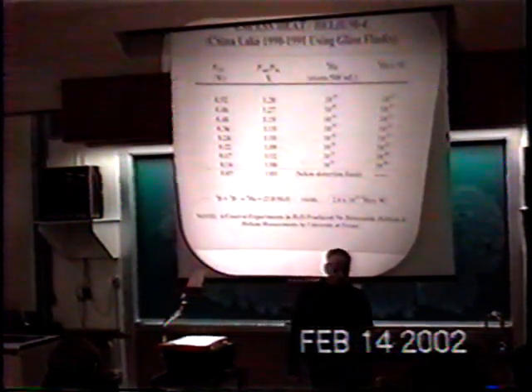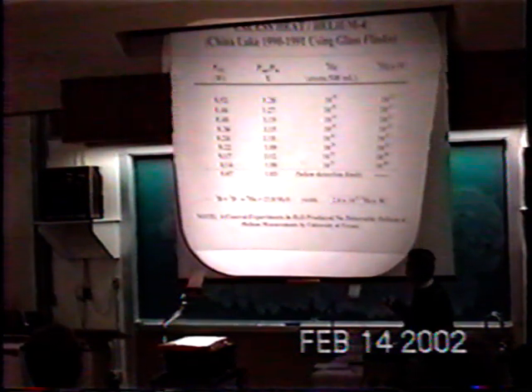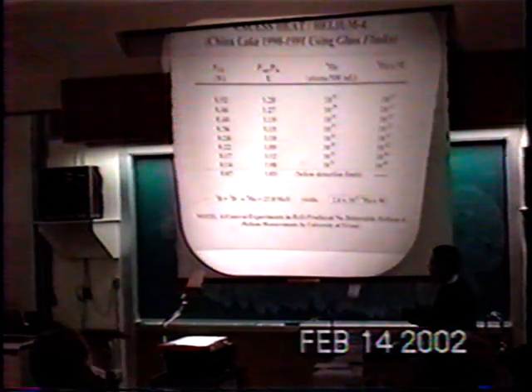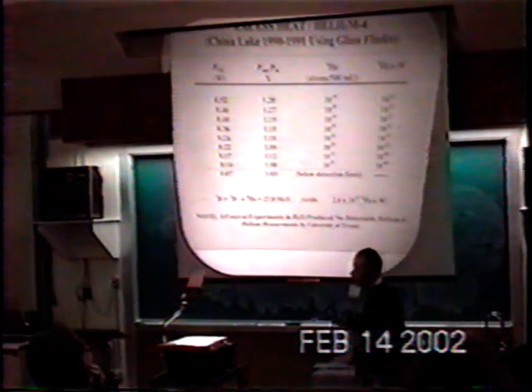Now, in our first study of excess heat and helium, we collected gas samples in a glass flask. We did not have the capability to measure helium-4 at China Lake, so I shipped these to the University of Texas in collaboration with Ben Bush, who was there. We could only get order of magnitude levels of helium-4 measurements, but when we had excess heat, we had elevated levels of helium-4. These are around 10 to the 10, 10 to the 11, 10 to the 12 helium atoms per second per watt. This reaction theoretically produces 2.6 times 10 to the 11 helium atoms per second per watt. So we're within an order of magnitude, between 10 to the 10 and 10 to the 12.